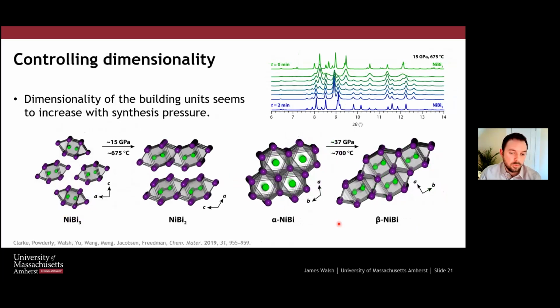And so another example from the nickel bismuth system. Now we're taking the other known intermetallic. Again, this is something that we can make under ambient or normal solid state conditions, nickel bismuth 3. When we heat this under 15 GPa, we get a transformation into this nickel bismuth 2 phase. This is a new solid state phase that was published.